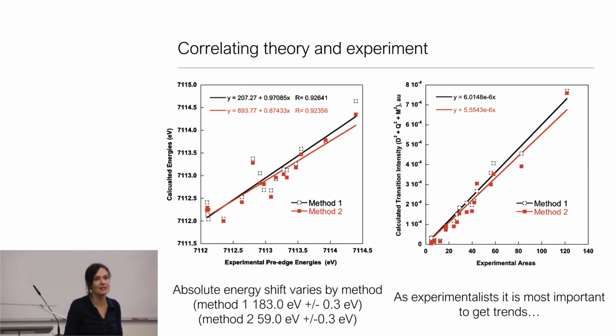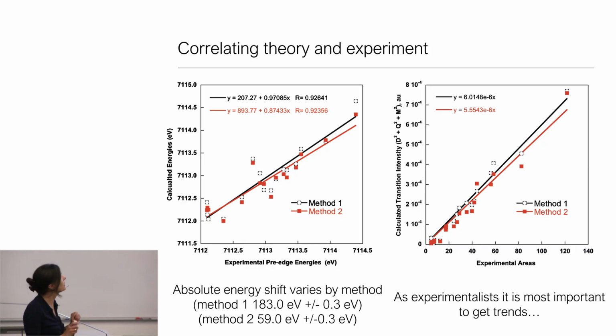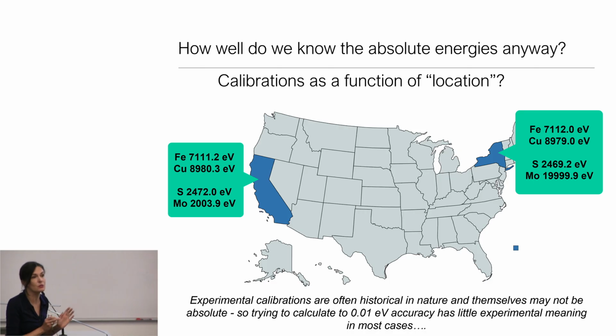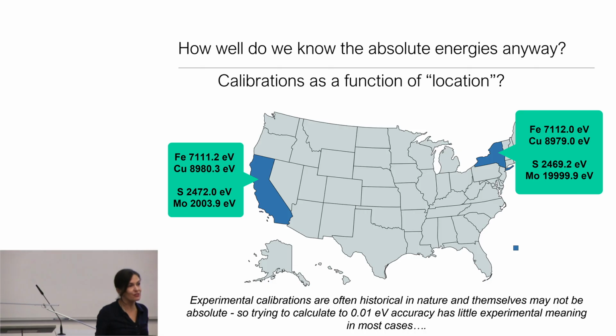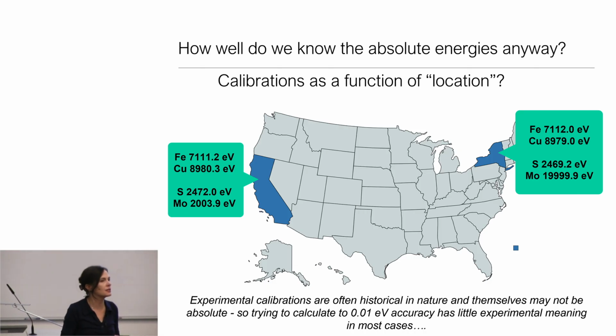And the reason I say this is because, as much as an experiment is forever, you also have to be honest with what we as experimentalists actually know. How accurately do we actually know our energies? And the reality is that we all calibrate. We have different reference books that we pull out. And if you look even in the US, I picked 2 synchrotrons. The iron at SSRL on the west coast of the United States is 7111.2 eV. But if you go over to Brookhaven Lab, it's moved by 0.8 eV. And it's not that iron has shifted, right? The foil is the foil, but simply that people have historically used different references.